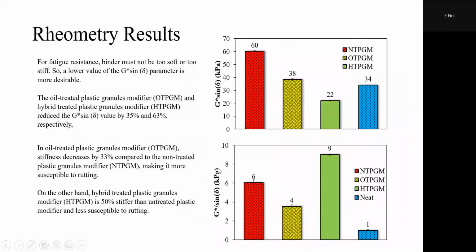And here you can see the factors for fatigue resistant and rotting resistant. These are a standard specification. You can see for the non-treated one here, the red, G star sine delta, which is a sign of fatigue, was 60. And then you can see the numbers reduce much more, which shows improvement in fatigue. They are different, the three of them, but their improvement here is noticeable.